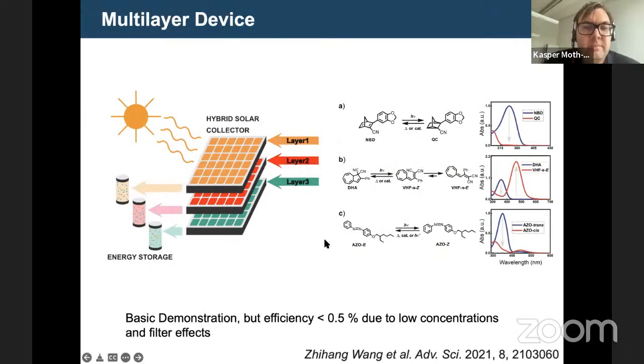Nevertheless, we recently built the first demonstration of this, where we combined 3 different classes of molecules: the norbornadienes, the DHA VHF, and the AZO system, all of them operating in different wavelengths, and we put them on top of each other. Still, the actual efficiency of the energy capture is relatively low, but in this case, better than any of the systems alone.